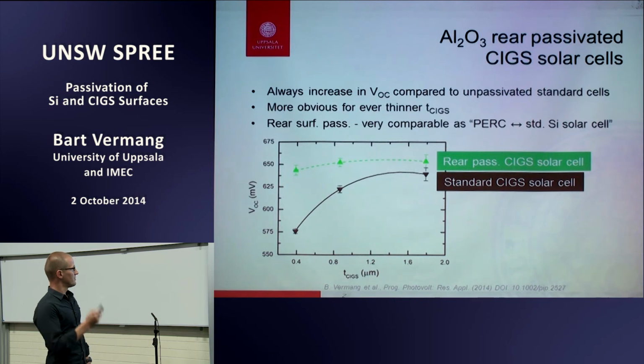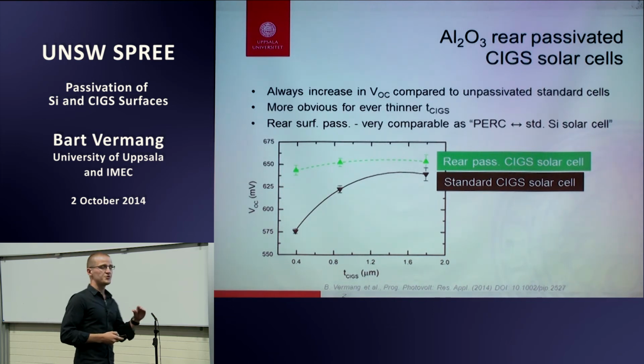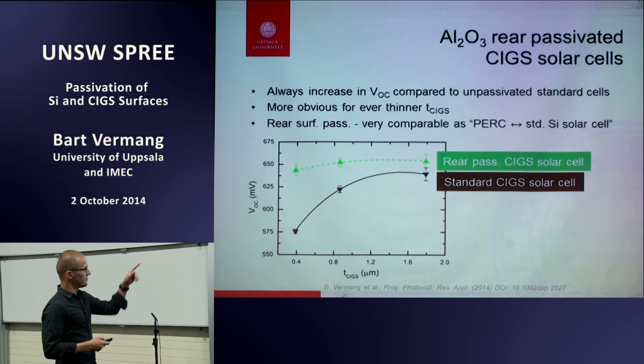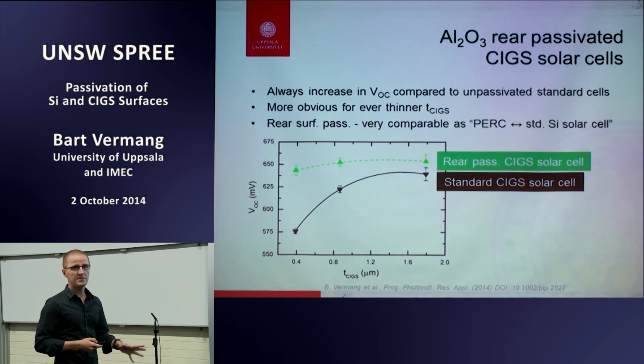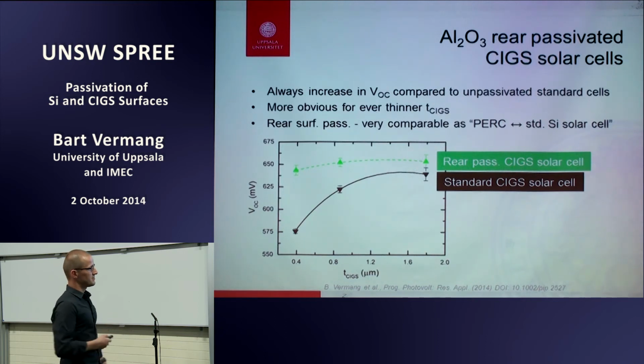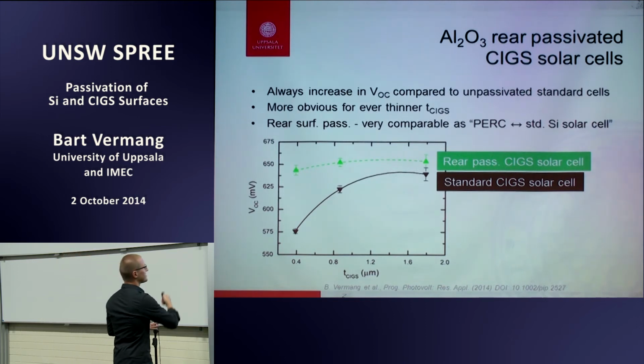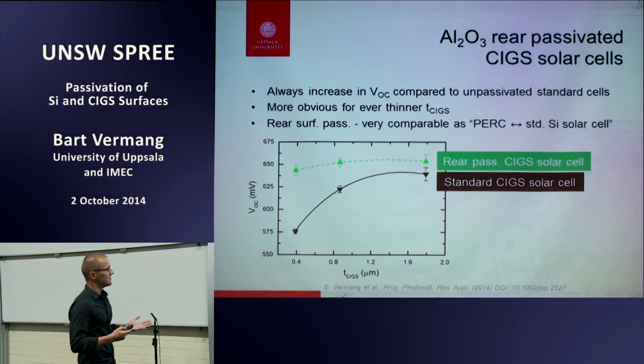And if we plot now VOC as a function of the absorber layer thickness for the rear-passivated cells in green and standard cells without the passivation layer in black, it's the same idea as with PERC. If you go for thinner cells, you should start to see the effect of the passivation. And you see it.